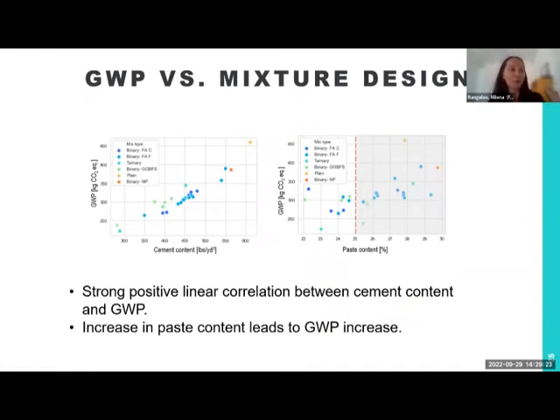This first graph on the left-hand side is showing the correlation between cement content and GWP, global warming potential, in kilograms of CO2 equivalent. We can see very strong linear correlation between the two. And then these mixes are summarized in different colors based on the mixture type. So there are differences in different clusters of the mix, if you will, based on the mix types. However, regardless, across the board, we have very prominent positive linear correlation between cement and GWP. Higher cement, more GWP, period.